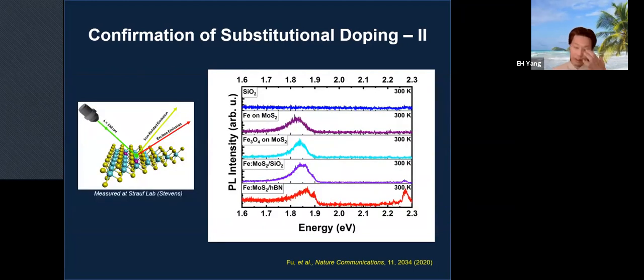Another confirmation was done using photoluminescence measurements using the control samples. So the bottom 2 are iron doped samples, and the top 3 are control samples, basically SiO2 and the iron film and iron oxide powders on MoS2. Again, you don't see any peaks there, but you see these peaks from these iron doped samples only.